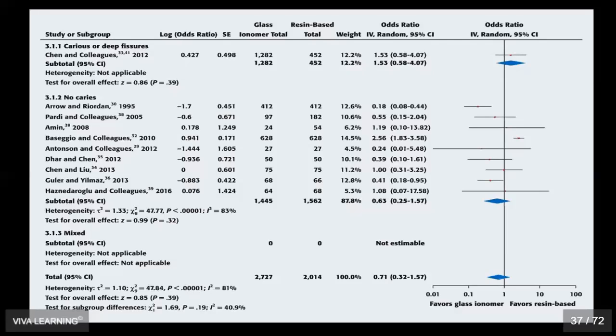So let me orient you to what this forest plot is. Each one of these lines, like Chen and colleagues in 2012, Arrow and Riordan in 1995, Pardi and colleagues in 2005, Amin in 2008, these are all the studies that we looked at, which informed our decision to figure out which sealant material prevents caries lesions better. Is it a resin-based sealant material, or is it a glass ionomer sealant material? Now, Chen and colleagues were looking at carious fissures or deep fissures. They looked at 1,282 glass ionomer sealants, 452 resin-based sealants, and what they found was when you're applying it to carious or deep fissures, it looks like resin-based sealant materials actually are better at preventing and reversing caries lesions.